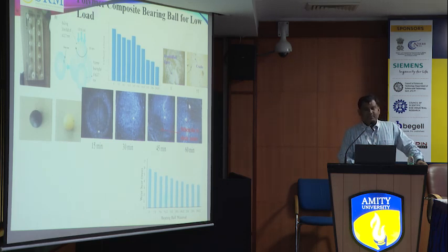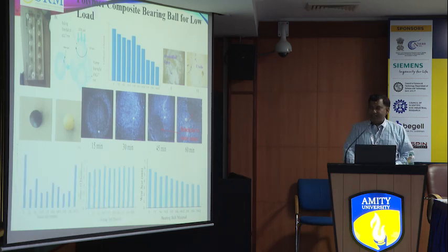So that is also used for low load applications, like in your chairs. You can use it where no lubrication is required. It is very helpful. And if your wear scar is less than 4 mm, then it is acceptable in range, that is the ASTM standard. So the graphite talc bearing ball is acceptable in nature.